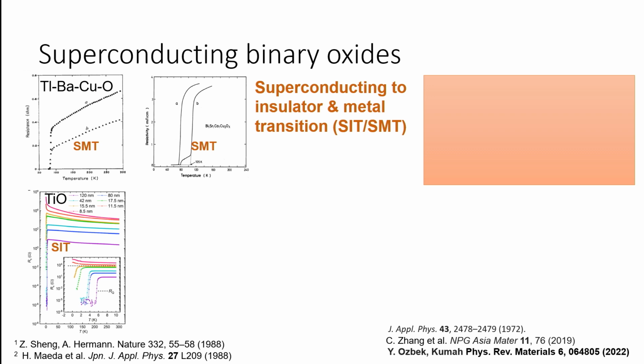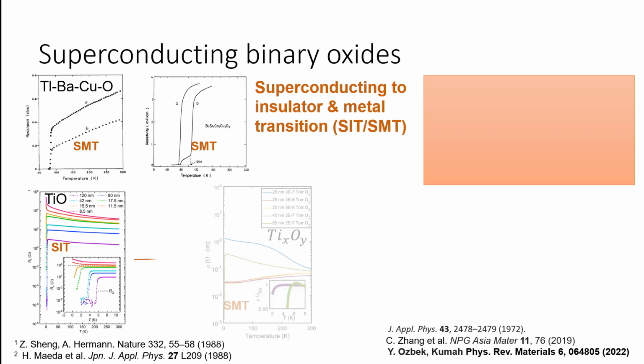But one thing you see that's different here is that, first of all, you have to increase the thickness of the TiO to about 120 nanometers to maximize TC. And the resistance goes up before it goes down, unlike what you see in a lot of the other superconducting systems. So we've been able to grow these materials using molecular beam epitaxy. We've varied the oxygen pressure, we've varied the thickness, and we can get a wide range of interesting properties. We can also reproduce the same kind of up and down behavior.